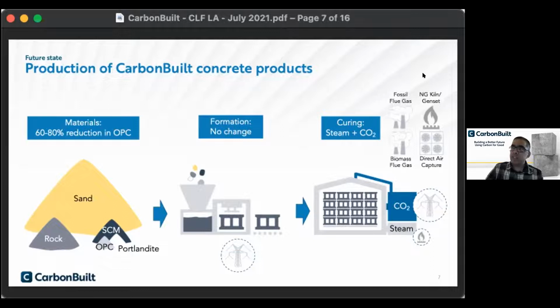And in addition to the CSH products, which are the main products of hydrating cement, you also get lots of calcium hydroxide. Again, this is sort of evolved Portlandite in the hydration process. Typically, that's what fly ash can take advantage of. So the components of fly ash combine with this evolved calcium hydroxide over days and weeks. So this is a much longer process to form more of the CSH products that deliver concrete strength. Okay, so to that process, we are adding Portlandite carbonation.